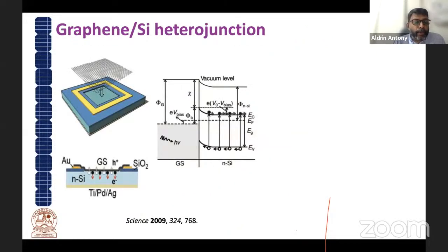And here I'm showing something using graphene as a carrier selectivity layer. Graphene does not have any band gap, but it has a work function, and when it comes in contact with N-type silicon, the bands bend in this direction, forming a Schottky junction with the crystalline silicon. When it is illuminated, there's a barrier for the electrons, and only the holes will be transported into the graphene. So graphene works as a very good hole transporting layer with the N-type silicon.